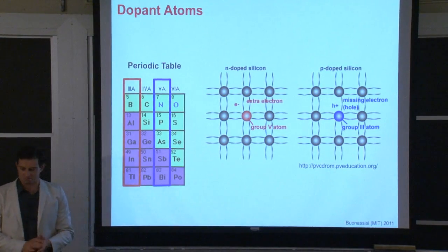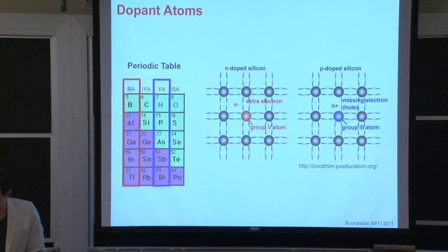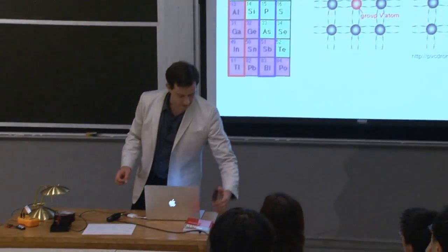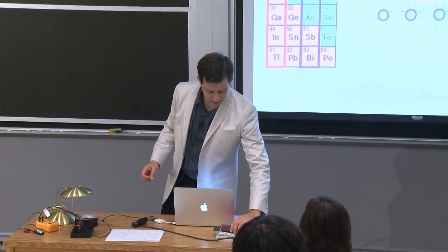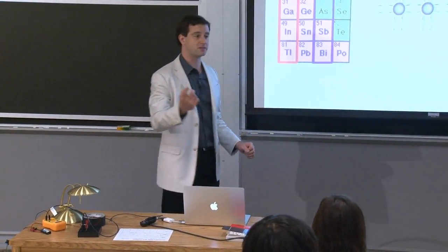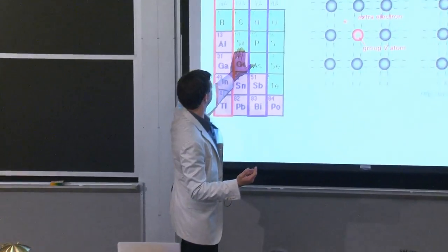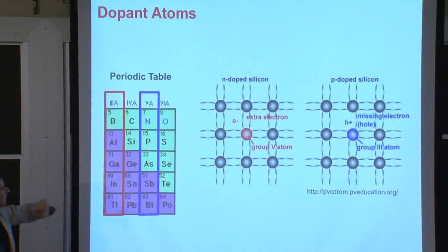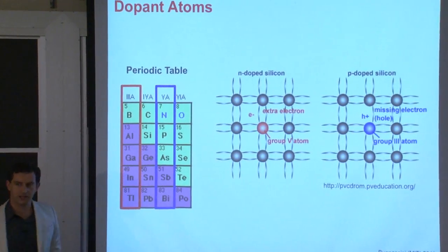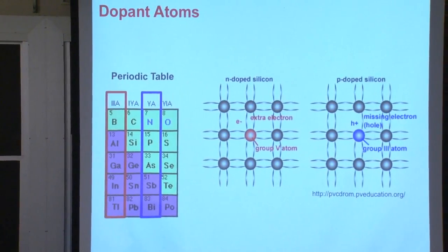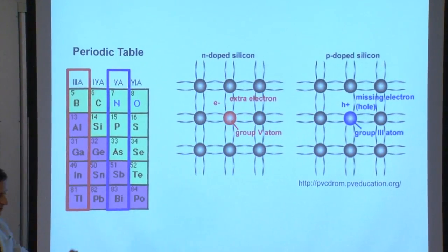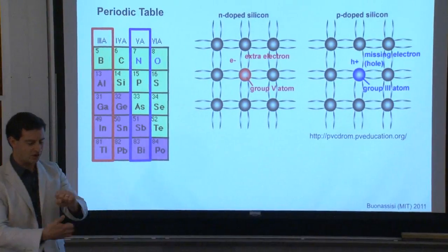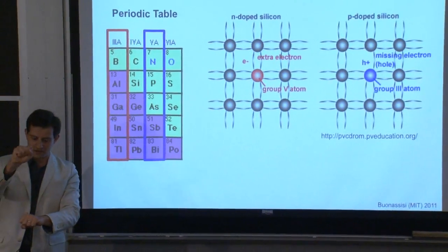So if we look at a semiconductor such as silicon, this is a little piece of silicon right here. Here's a silicon-based solar cell. It's a fairly easy semiconductor to understand. It's what's called a unary semiconductor, meaning it's comprised of one element, silicon, right here in the periodic table. This is just an excerpt from the rightmost side of the periodic table. And silicon has 4 valence electrons, so it forms what are called sp3 hybridized orbitals when it's in a crystal structure. It has 4 bonds with its nearest neighbors, all of equivalent type, and those are covalent bonds.